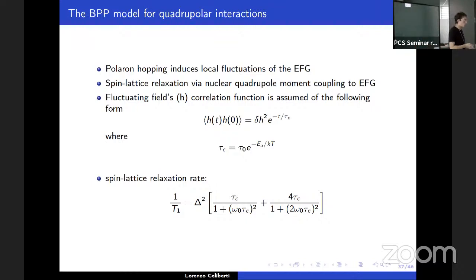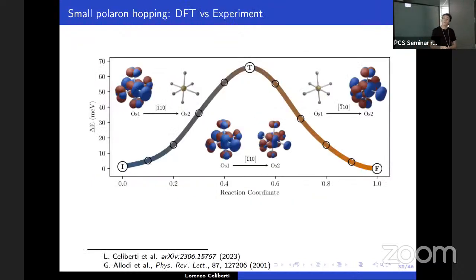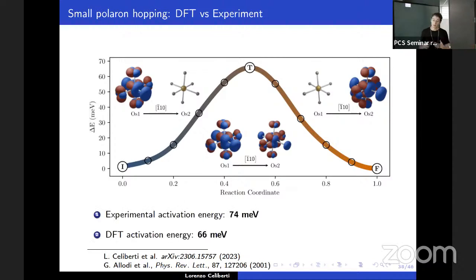And for polarons, we can also model this with DFT. This is usually done with a linear interpolation scheme, where you take two polaronic configurations, I and F, and you interpolate the deformation between these two configurations, and you do one DFT calculation at each configuration. And you obtain this kind of hopping barrier, where the height of this barrier is what you use as an estimation of the activation energy for the hopping process. And this gave a very nice comparison with experiments. This is a kind of delicate point, but if you're interested in this, we can discuss it later.